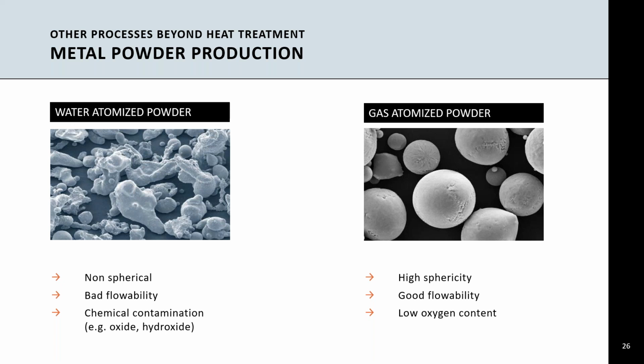The quality of the metal powder used will have major influences on the properties, but it can also influence build-to-build consistencies, the repeatability of the additive manufacturing machines, the production of defect-free components, and the manufacturing of defects on the surface as well. So if you see here in the image, you have water atomized powder as well as gas atomized powder, and kind of what they're best used for. Gas atomized powder flows more easily and has low oxygen content, whereas water atomized powder is non-spherical, has bad flowability, tends to clog up easier, and grabs hold of chemical contaminants as well.